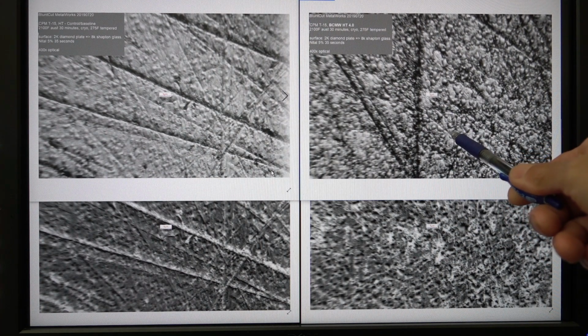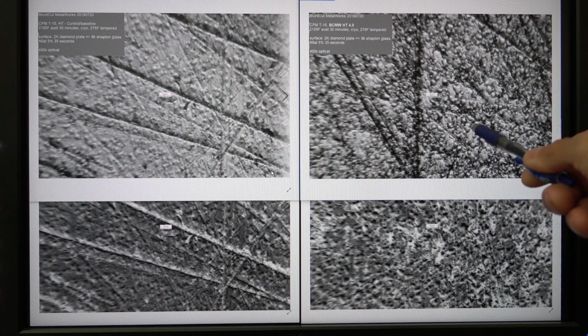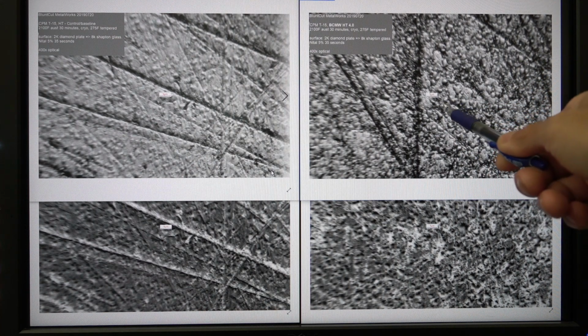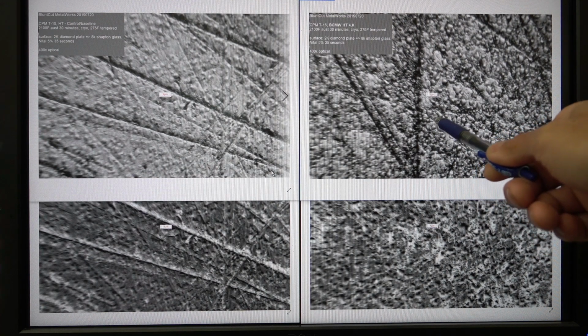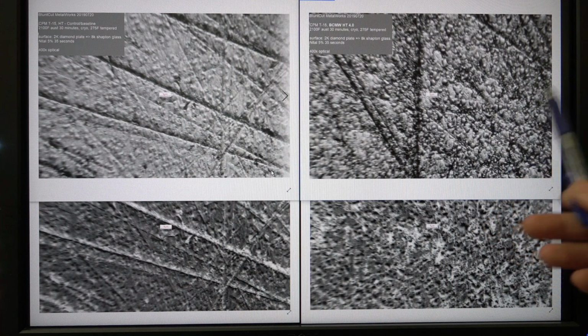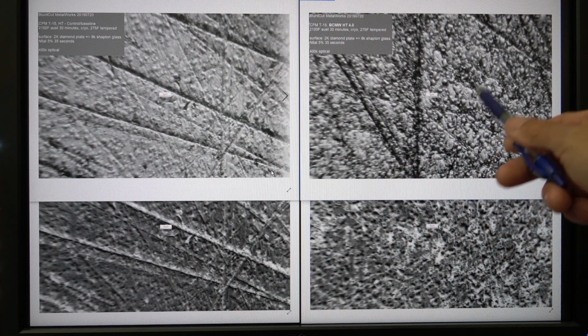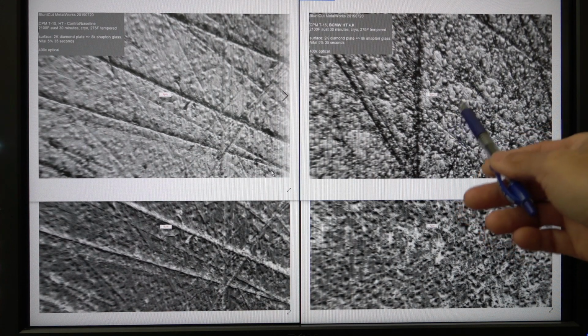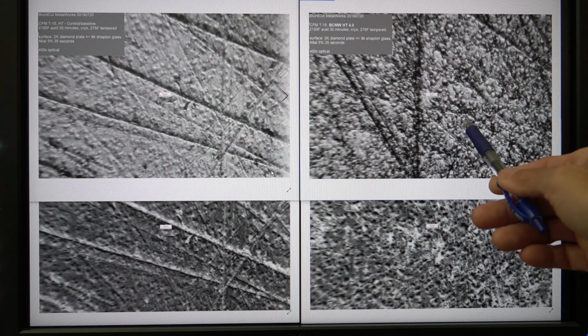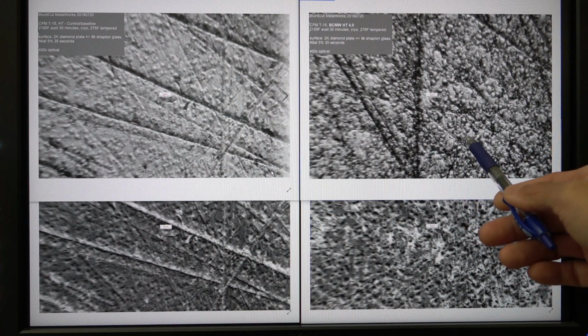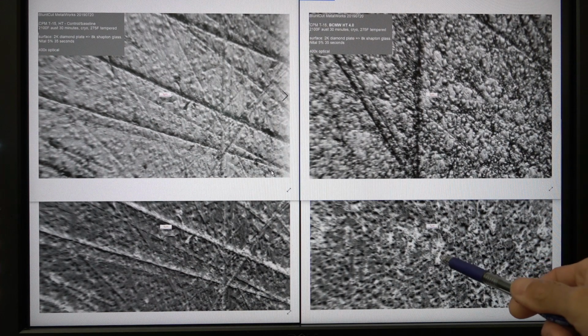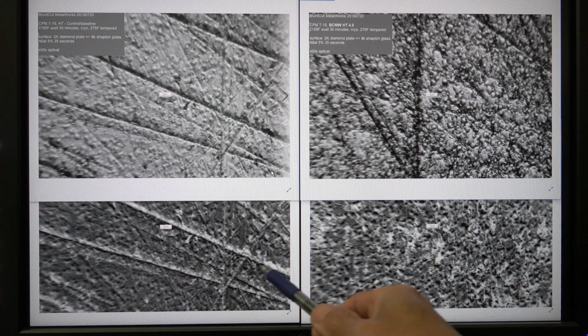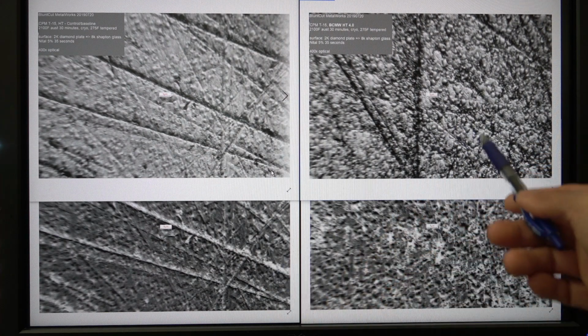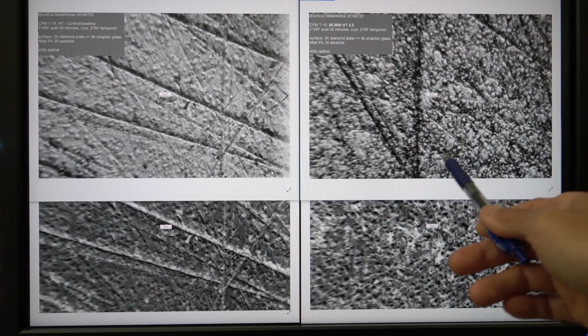Versus, you can clearly see the carbide, all the lumpiness, in the heat treat 4.0. In other words, there's a lot of the carbide still present. That means now the foreign material is going to rub against the carbide more. So you have this surface protected by carbides more. In other words, this matrix is stronger at holding on to the carbide. And in the inverted picture, you can see the depth of this hole and the number of them compared to the two. This versus this will tell you that for T15 it is a large improvement. 10V also has a large improvement, but T15 is more pronounced right here.